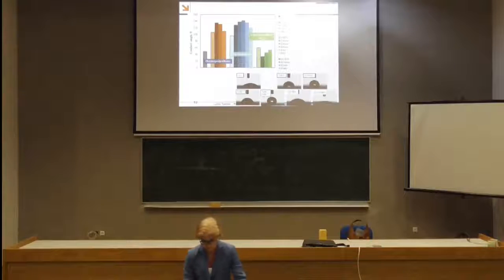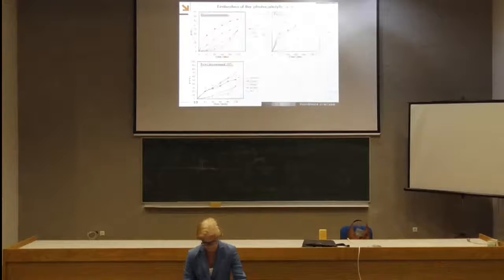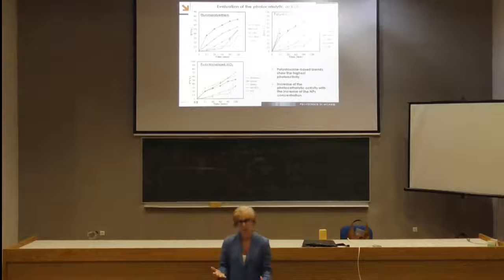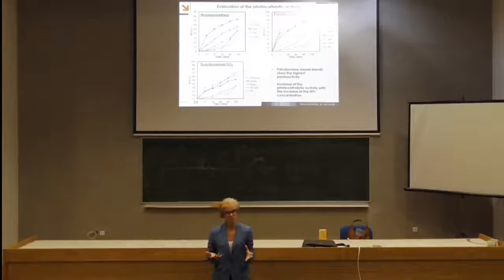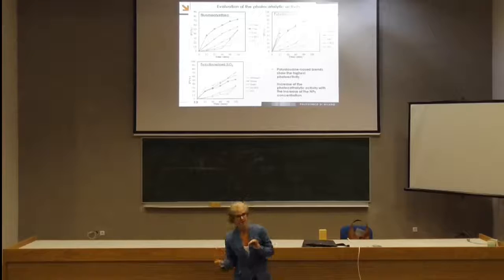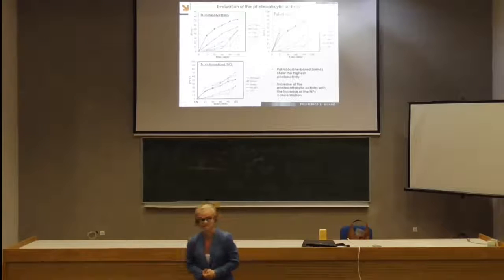And these are the experiments, of course, the contact angle measurements. And these are the photocatalytic effects. So we got, in this case, very nice results. That is, the increase in roughness of the substrate, the nano dimension increase, is very good for water repellency, and at the same time is very good for photocatalytic effect. So we combined two properties of these nanoparticles to give a double result, to obtain not a self-cleaning hydrophilic treatment, but a super hydrophobic substrate. So this was a very, very good result.